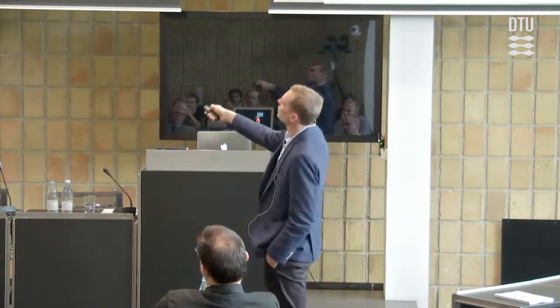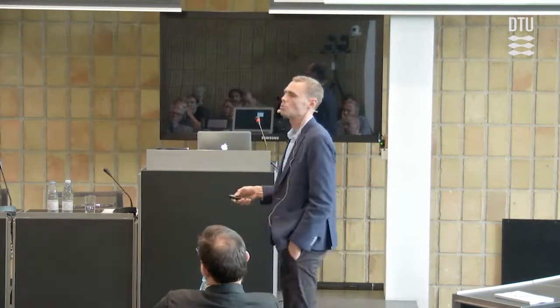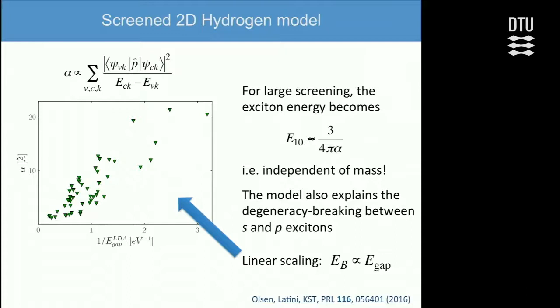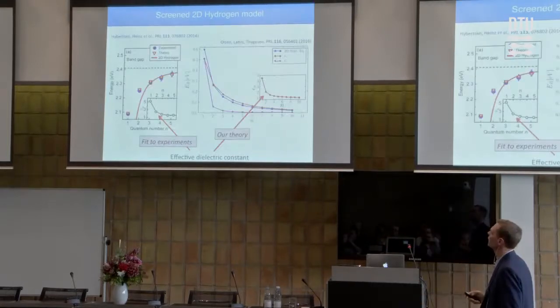Another thing the model explains is the observed linear scaling between the exciton binding energy and the band gap of the material, because the polarizability alpha, or dielectric constant of the material, goes roughly as 1 over the band gap. So that's also well explained by this expression.